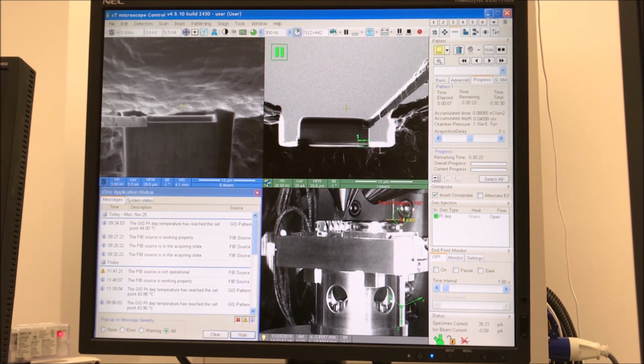So the advantage of mounting the lamellas like this is because you have them fixed on both sides, they're less prone to warping and deformation when they get really thin, as opposed to some other methods where they just attach the lamella on one side and then they thin it. You can end up with the lamella curling or bending in on itself, and that obviously can make it harder to image in the TEM. So doing this just provides more mechanical stability.